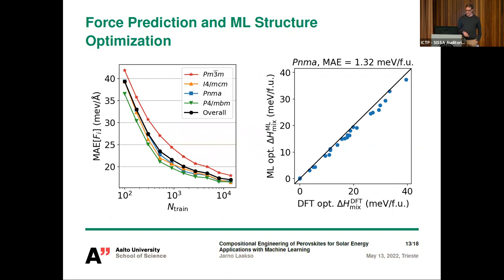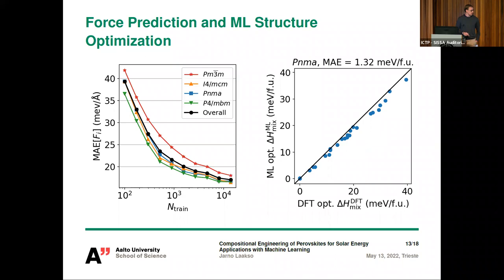For force predictions, the learning curves show that we reach force component prediction errors of less than 20 meV/Å for all phases. On the right are relaxation test results: the x-axis shows DFT-optimized energies and the y-axis shows machine-learning-relaxed energies, shown for Pnma structures since those are used in the convex hull computations. For the relaxations our error is only 1.32 meV per formula unit.